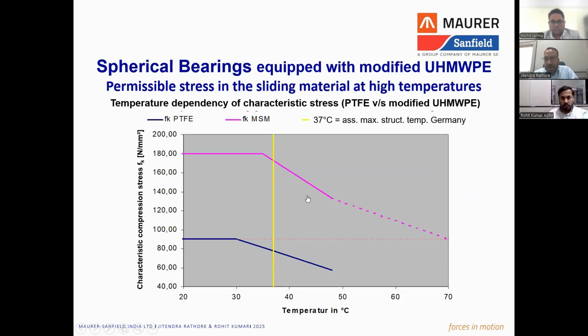This is a temperature graph. I have the values here compared between PTFE and UHMWPE. The original or initial strength of both the materials is different. UHMWPE has double strength, but it is also a thermoplastic material. So it is important for you to understand that it also has sensitivity to temperature. And when the temperature exceeds beyond 35, which is the threshold value for UHMWPE, 30 is the value for PTFE, there is again a reduction in the pressure applied for this material also. But you can see around 50 degrees centigrade, even the residual strength of these innovative approved sliding materials is much higher than the original strength of PTFE. So they are advantageous in any environment and any temperature application.